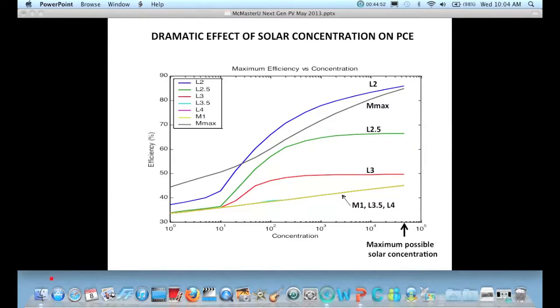As I mentioned, I'm going to stop in a few minutes. If you combine the carrier multiplication with these various characteristics that I defined earlier, and this is bulk, all semiconductors will have a higher efficiency if you concentrate the light. It's essentially like making the sun bigger in the sky so that the re-radiation loss is lower and the back dark current is not increased very much, and the photocurrent is increased, so you get a gain in efficiency with increased concentration.